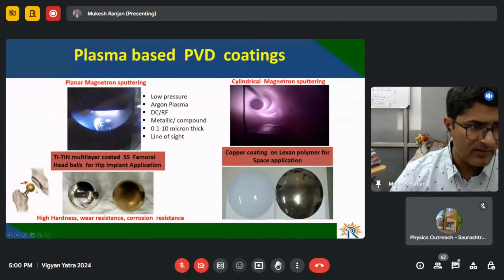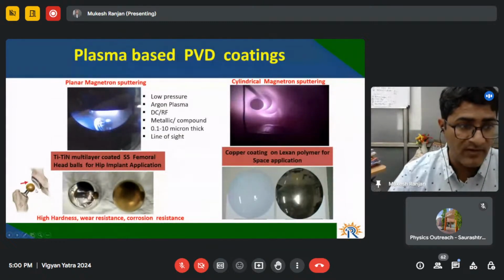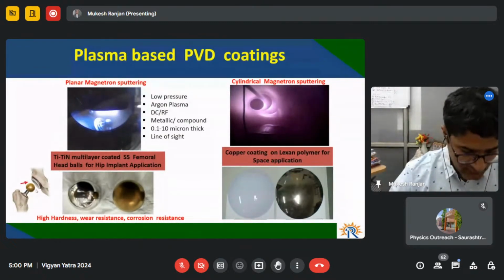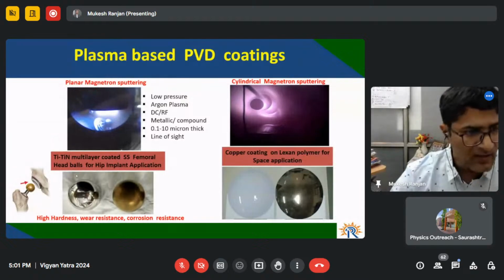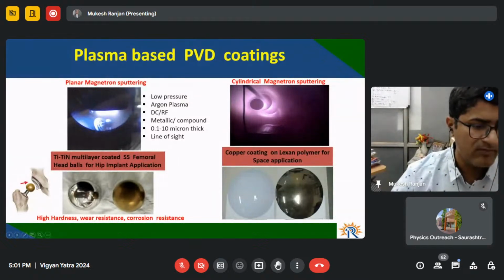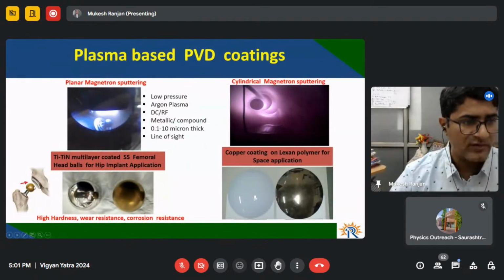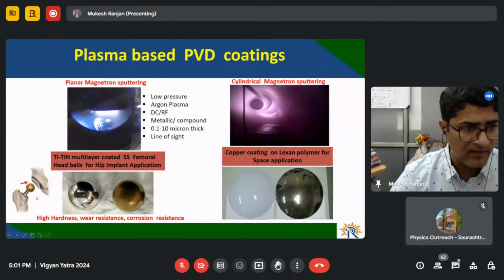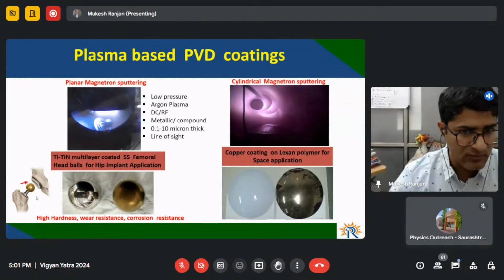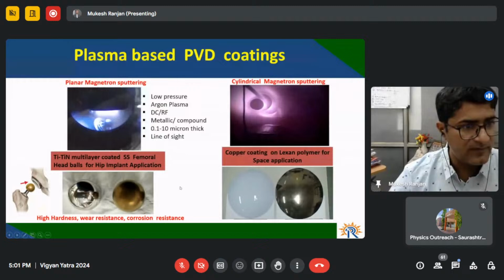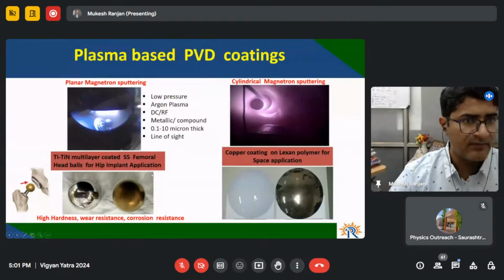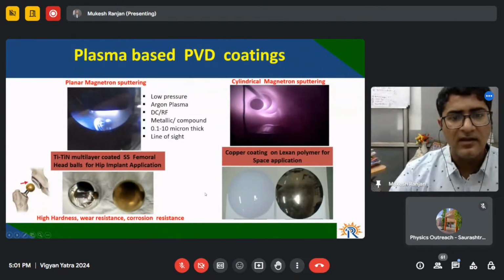So in this hip joint, the requirement is that it should be long lasting, after several cycles of movement. And whatever coating is used should be biocompatible. Okay, so titanium nitride is proven to be a very biocompatible and very hard coating, and that's the reason it is nowadays used for many biomedical applications like hip joints, and in your tooth also the screws are made of titanium nitride. So we have successfully developed this titanium nitride coating using the PVD coating.